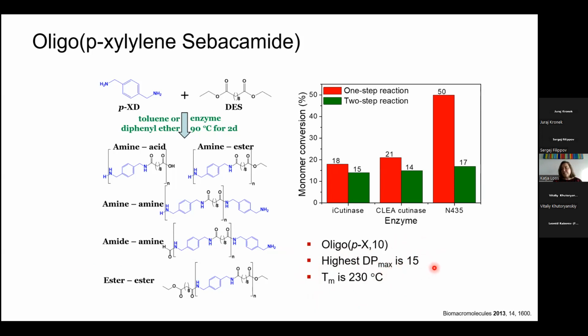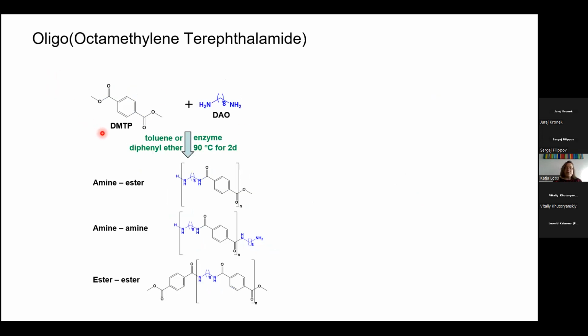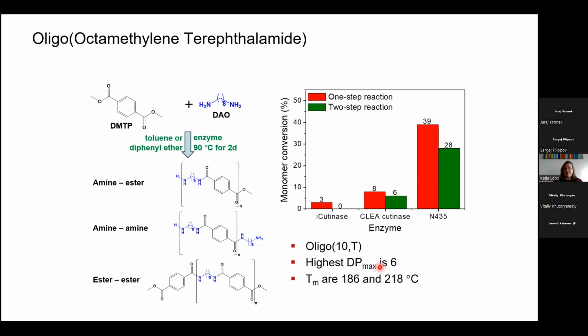And then if you do a post condensation, these are high performance polymers, and you do the pre-polymers in a green enzymatic way. And the same if you have the aromatic diacid and the aliphatic diamine. It also works very well here. The degree of polymerization, the maximum, is even lower, but you again have very high melting points. So even aromatic structures work, and you get very interesting polymers.